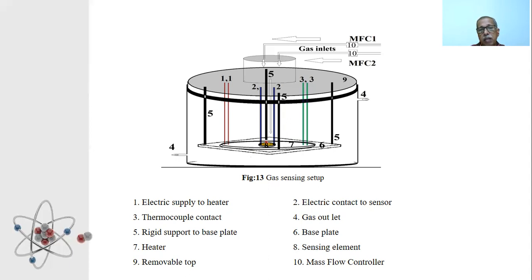Our material is pelletized. The size of the pellet is 13 mm diameter and approximately 1 mm thickness. It is kept at the selected operating temperature. Sufficient time is given for stabilizing the resistance. The stable resistance is denoted as R0 in air. Then the test gas is allowed to flow through the system. The flow rate is fixed using mass flow controller. Flow time is fixed as 10 minutes. At the end of the flow time, the resistance falls to a minimum value and it stabilizes there. The value is taken as Rg in test gas. Then the experiment is repeated using air flow to flow through the system for regaining the resistance back to the initial value. Then the experiment is repeated by changing the flow rate and changing the operating temperature.